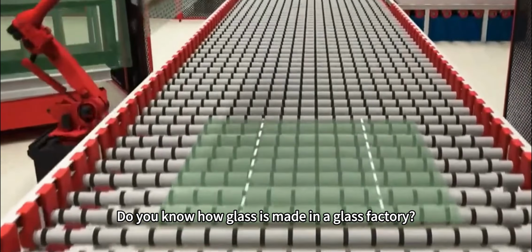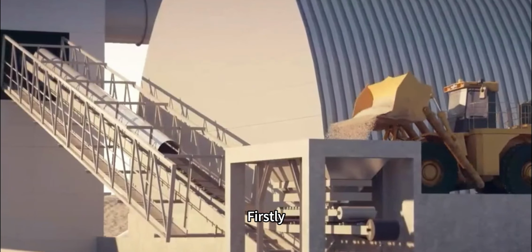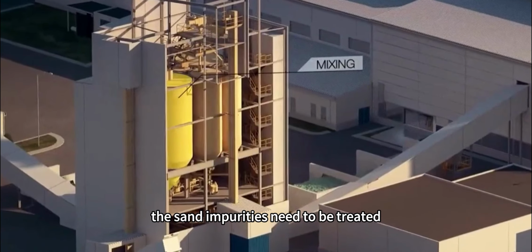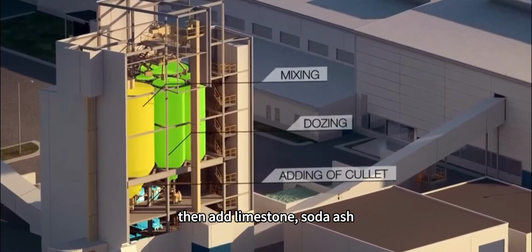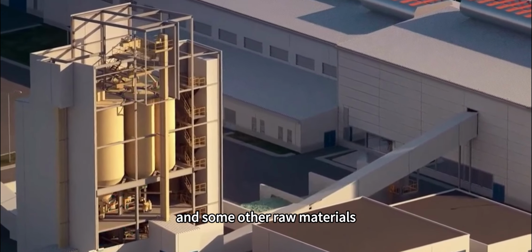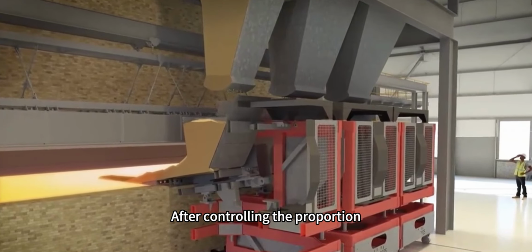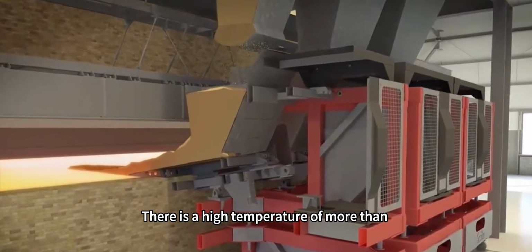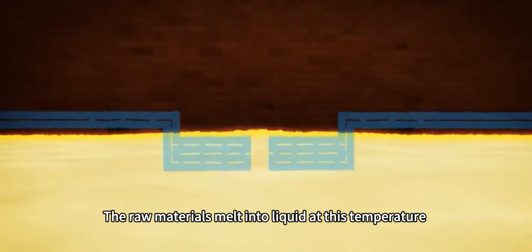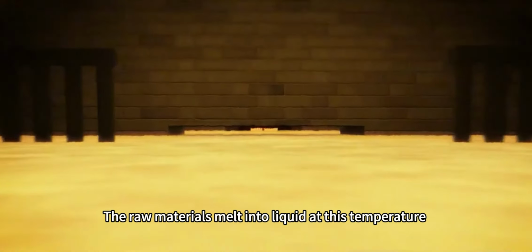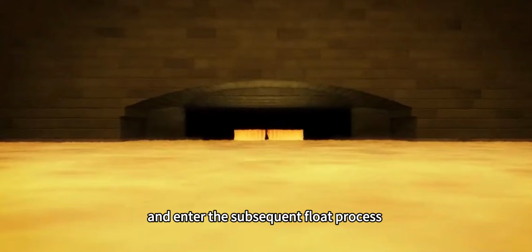Do you know how glass is made in a glass factory? First, the sand impurities need to be treated, then add limestone, soda ash, cullet, and some other raw materials. After controlling the proportion, they are sent to the furnace. There is a high temperature of more than 1600 degrees Celsius in the furnace. The raw materials melt into liquid at this temperature and enter the subsequent float process.